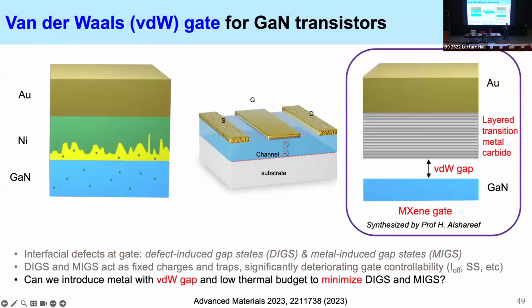So the question is, can we introduce a novel metal with the so-called van der Waals gap between the metal and gallium nitride? Because of that, we can basically minimize these two gap states, DIGS and MIGS. And it happened to be that Professor Husam Alshareef is an expert in synthesizing MXene. He has published many papers related to MXene, mostly for energy applications.